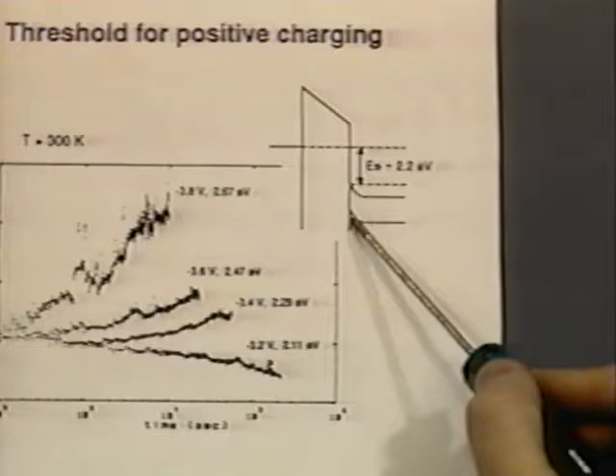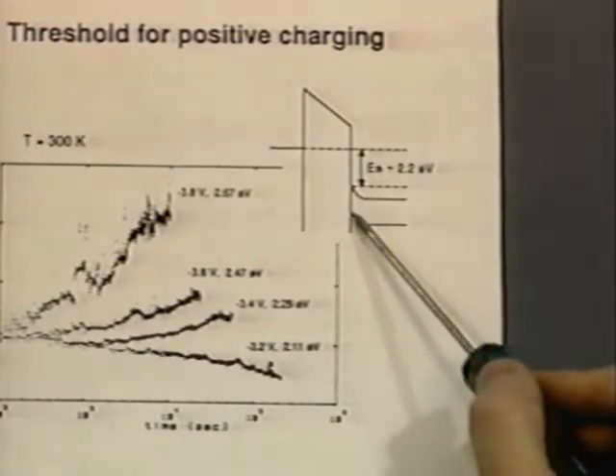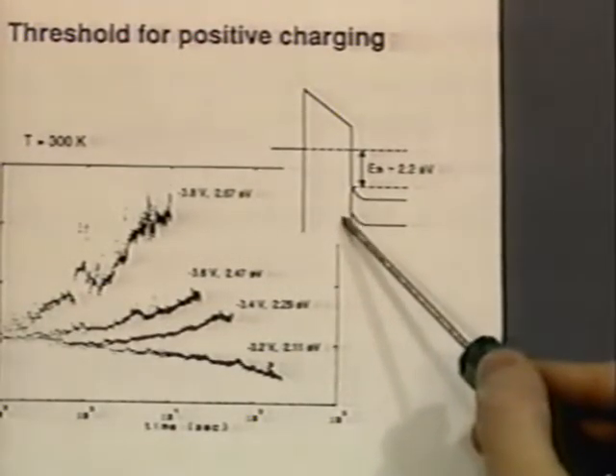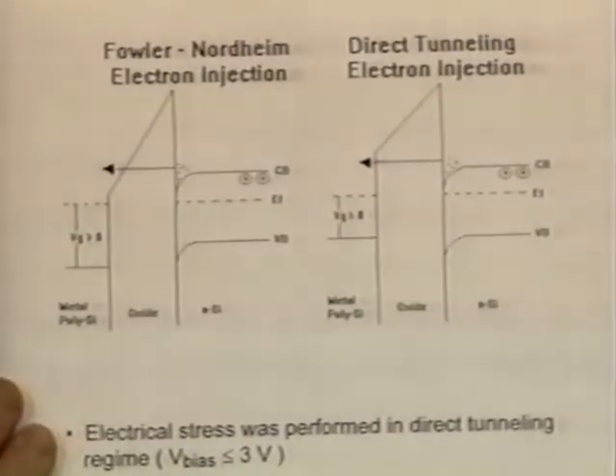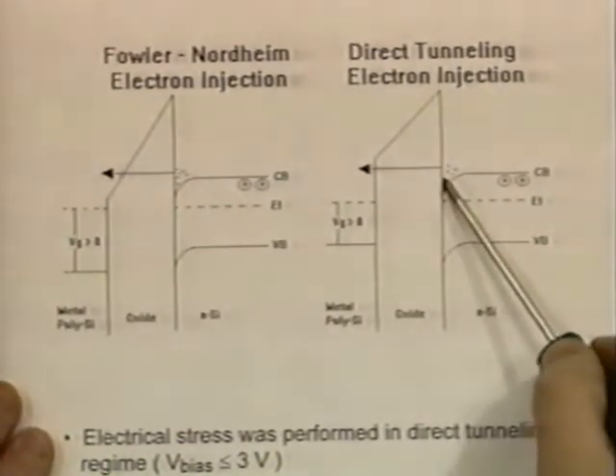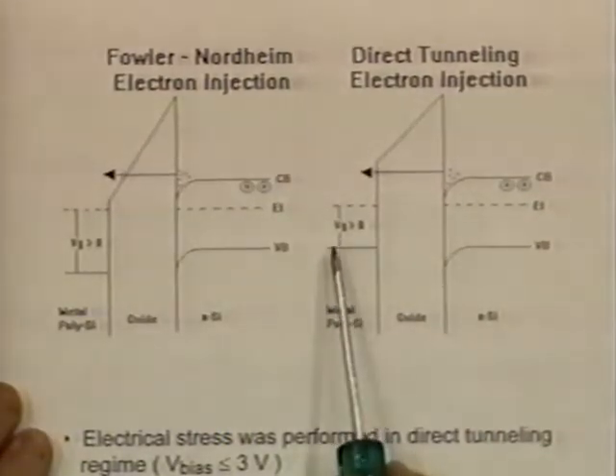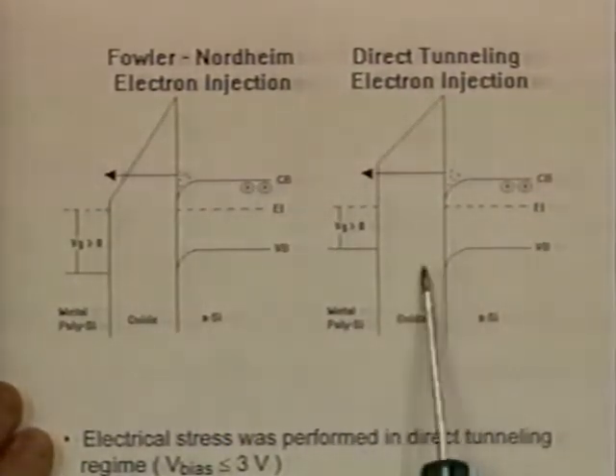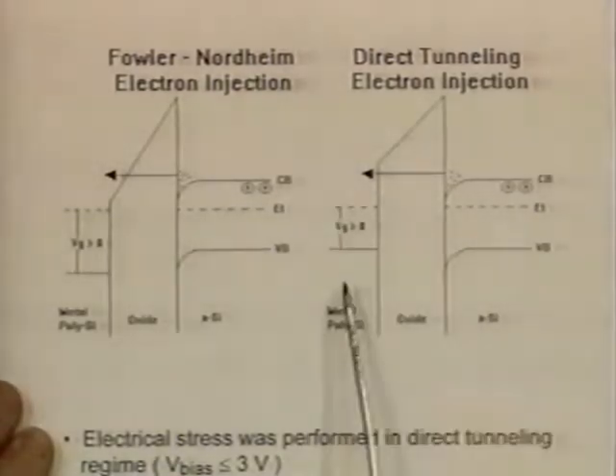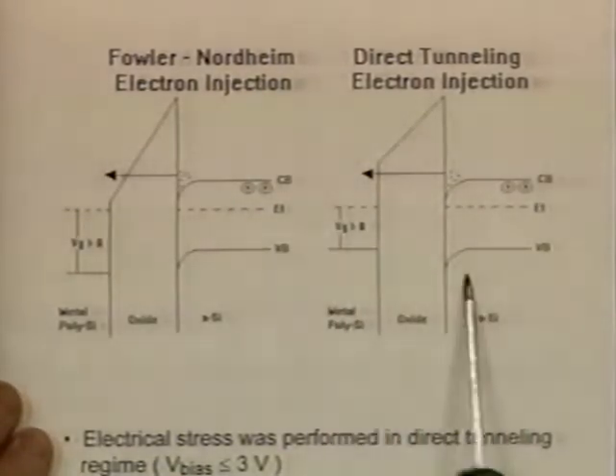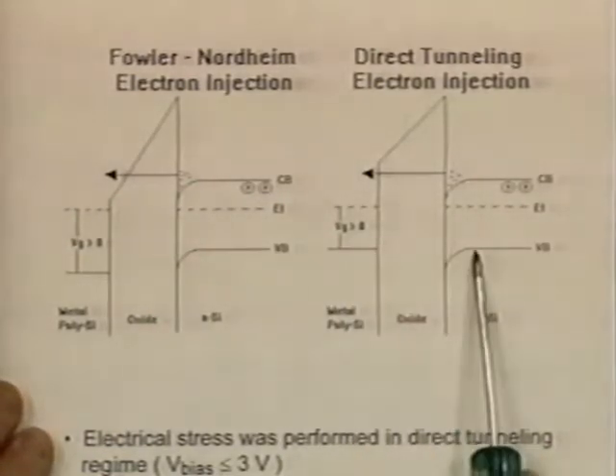Now, so what you're doing is you have more and more holes which can attempt to do whatever they're going to do for creating a defect. That's one side, and let me get the other band diagram for you for N-type. For N-type, well, certainly you have accumulation of electrons, but the threshold occurs when this level here is below this level here. So not only do you have electrons going here, but you may have some holes going in this direction here. And so as you change this voltage, you have a greater hole current going back in this direction.